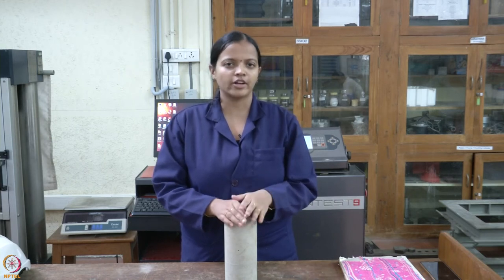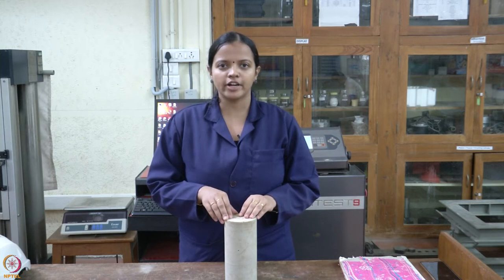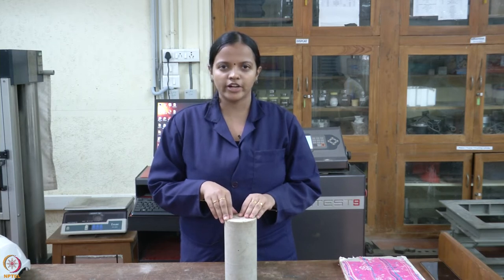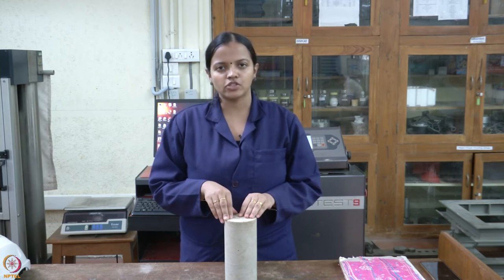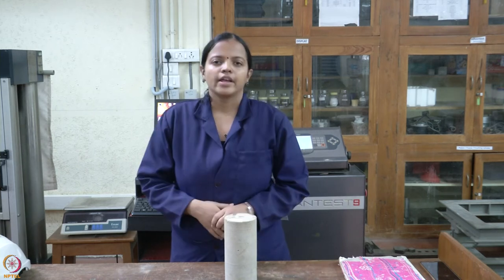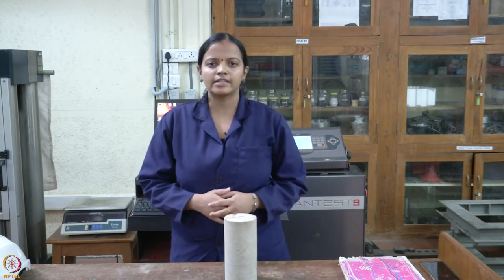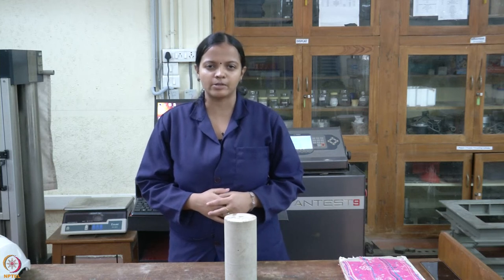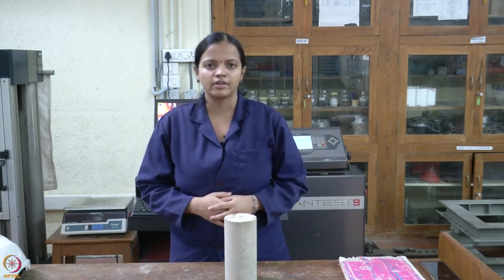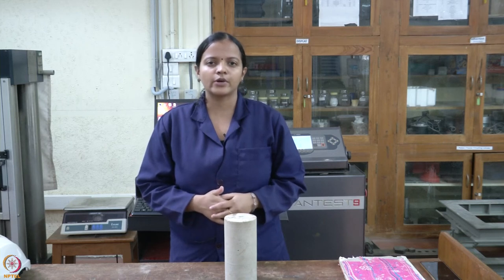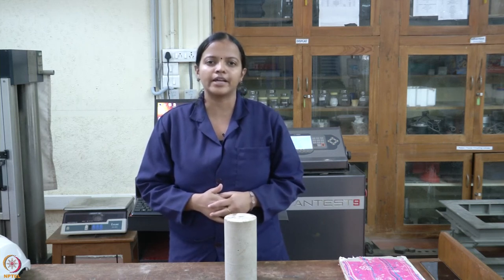From this test, we can derive the Young's modulus of concrete from the linear region, and you can calculate the compressive strength of concrete. By using the axial and circumferential strain, you can calculate the Poisson's ratio, and you can also calculate the compressive toughness, which is the area under the complete stress strain curve. In the conventional testing procedure, this type of result is not possible, where you can get the complete stress strain curve. By using closed loop testing, you can have a stable control and get the complete stress strain curve.